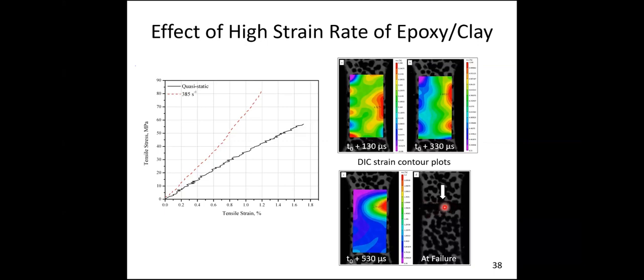So what I want to convey from this slide is, if you use any extensometer or any strain gauge, you may get only the numerical data. But when we use this digital image correlation technique, it is possible for us to get the qualitative data, and also you will get more in-depth data from that given sample. So this is what I wanted to convey. As I mentioned earlier, the epoxy clay is very sensitive to strain rate. At quasi-static, it has different properties, whereas when I do the testing at high strain rate, say 385 per second, I have got different properties. So this is what I wanted to convey to this forum.